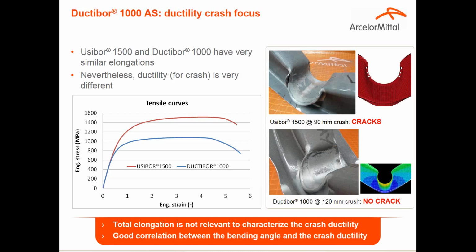On the left-hand side, you see the tensile curves of Usibor 1500 and Ductibor 1000, with similar elongation. But it doesn't mean that they present the same energy absorption. On the right-hand side, there is the proof that in the same conditions, the Ductibor 1000 can absorb much more energy than the Usibor 1500. In fact, these two grades work in different ways. Ductibor 1000 is to absorb energy, Usibor 1500 is to stop.